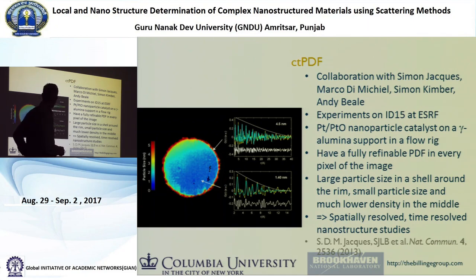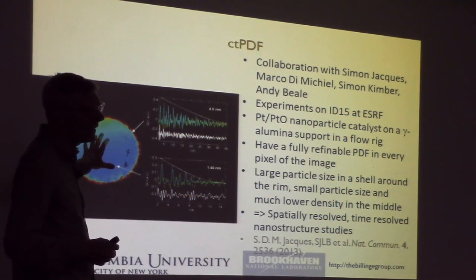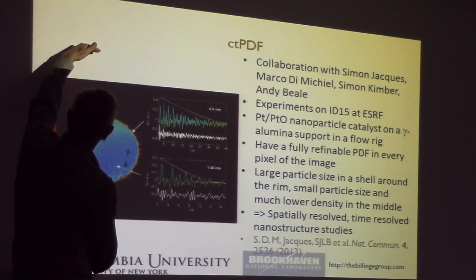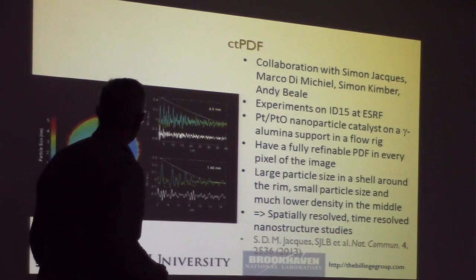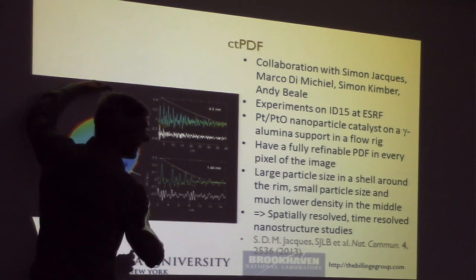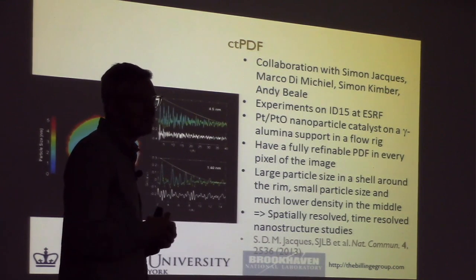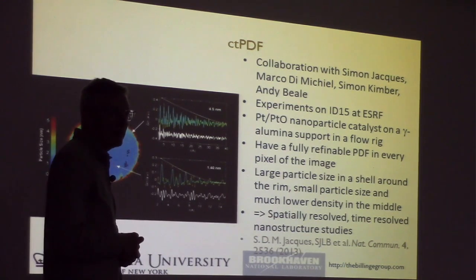So that's what we're doing here, but what we do is we have an object. This is actually a catalyst body, a stabilized alumina porous material, and sitting on top of it are platinum nanoparticles, they're very tiny. And what we do is we have a synchrotron down here, so our synchrotron beam comes up here, and our detector is back here. So we get the diffraction pattern, which is relevant for this position. And then we move across, and we get this position, this position, this position, this position. So we do a line scan of 100 points. And then we take this and we rotate it 2 degrees. And then we do it again, a line scan of 100. 2 degrees, line scan of 100. So we end up with roughly 100 by 100 data sets, so 10,000 data sets. And each data set is a complete diffraction pattern. So is the resolution ultimate here? So the resolution depends on the size of your beam. And so we were doing, in this experiment, 40 micron resolution, but we could do smaller.